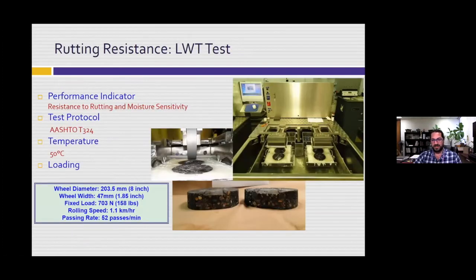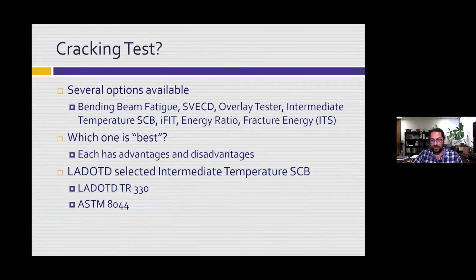So rutting resistance was pretty straightforward. We used the Hamburg loaded wheel tracking test. We've used it for a very long time here at DOT, so the comfort level was high. We actually had implemented this first, as an introduction into laboratory testing for our contractors. And this really eased the tension, in terms of having to get into laboratory testing, moving from volumetrics only. And then cracking tests, the big question is which test to use.